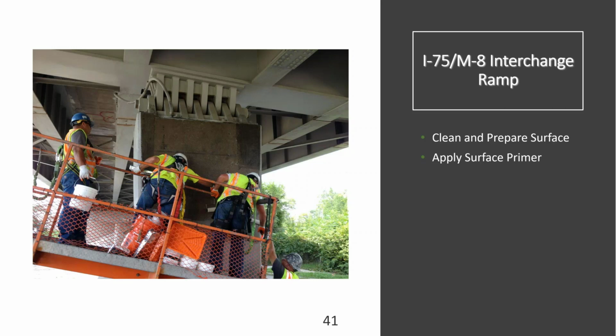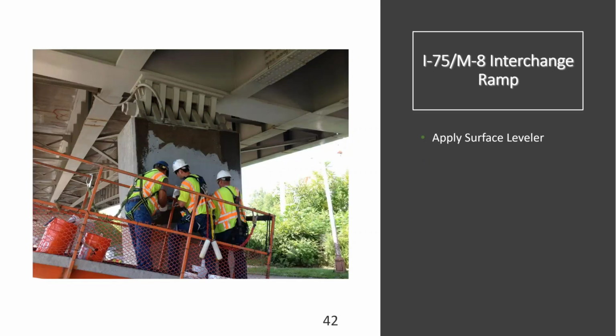The CSP3 shot blast also opens up the pores of the concrete to allow the epoxy to soak into the surface better, but we don't want to be more aggressive than that with our surface preparation, because then we start introducing more surface irregularities. So again, we did the CSP3 to just clean it and not have a lot of surface irregularities, so that we don't use as much of